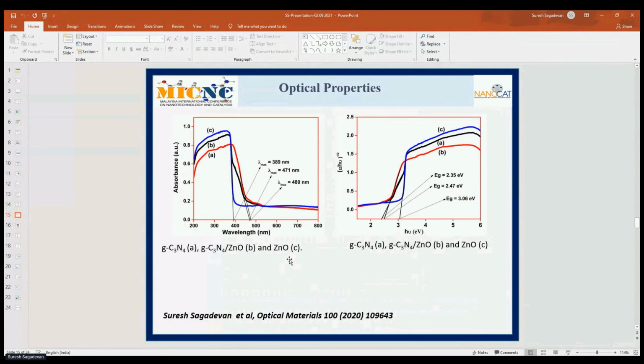Next, the optical properties. You can see the comparison of the UV spectra of graphitic carbon nitride, the composite, and zinc oxide. From this figure, we observe a significant redshift in the light absorption of the composite, indicating its photocatalytic efficiency in the visible light region. The maximum absorption wavelength of graphitic carbon nitride, A in red, is 480 nanometers. The composite, B in black, is 471 nanometers, and zinc oxide is 389 nanometers.